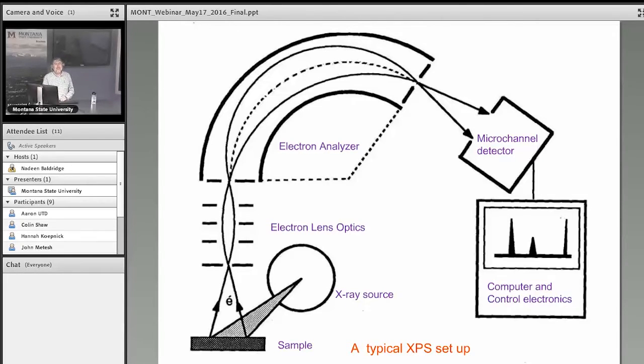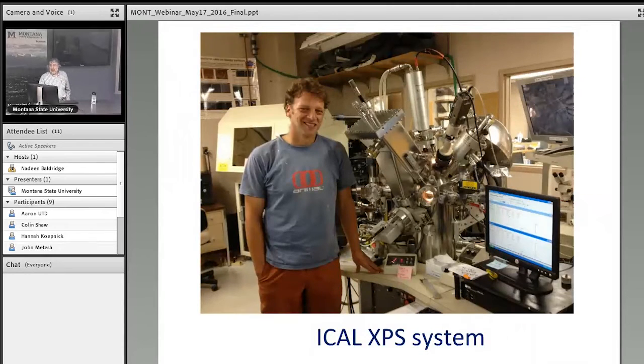So XPS is simply you shine X-rays on your target, it's about a millimeter in diameter, and then you analyze the kinetic energy of electrons from that, and you can get elemental identification. But you also get chemistry. Here is our XPS spectrometer. The X-rays are generated right here. This is our monochromator, focused on a target right here. This inverted Chinese wok looking thing is our analyzer, a spherical sector analyzer.